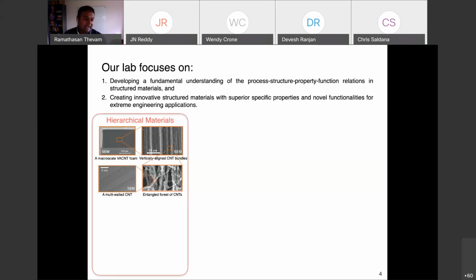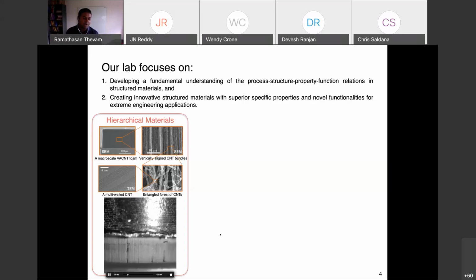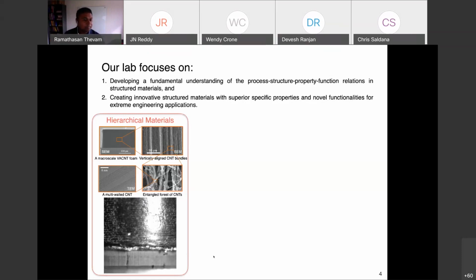That's what we do in our lab, and the outcome of that is, for example, you can see in this video, if you take this material and shoot it against a target attached to a striker, you see that it goes and deforms against the target in an orderly fashion, and it completely recovers back. During this process, it absorbs a lot of energy, in the order of more than 200 times the energy absorption by any commercial forms of similar density.